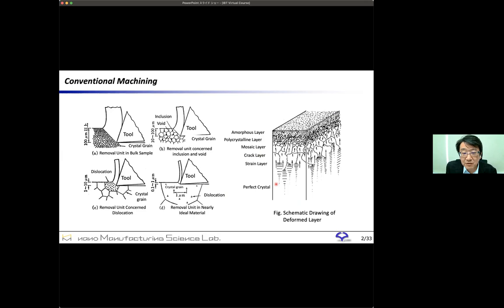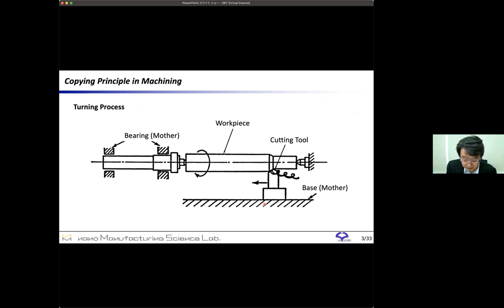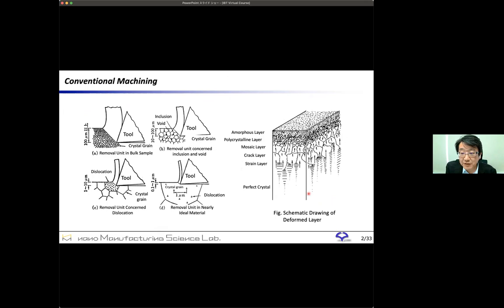The figure on the right side shows the surface deformed layer formed after machining. In the case of machining, the material is removed by plastic deformation, so such a damaged layer is inevitably formed on the surface. Such a damaged layer greatly deteriorates the physical and chemical properties of the material. The presence of the damaged layer is unacceptable in the case of functional materials such as semiconductors and fine ceramics.